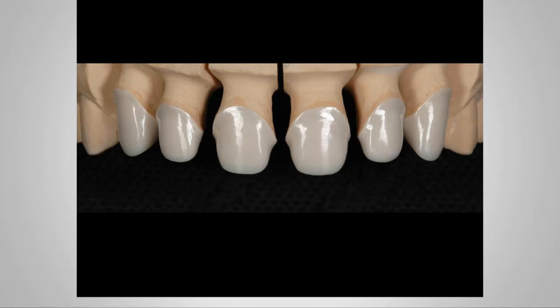So this is where we started with zirconia as coping materials, and as you know, we would add layering ceramic, which is a feldspathic type ceramic, over top of the coping, basically duplicating the same idea as we did with PFMs, or porcelain fused to metal. Now, while we of course get a better aesthetic value, we would not really have a stronger restoration because chipping was still seen quite often with the coping method.